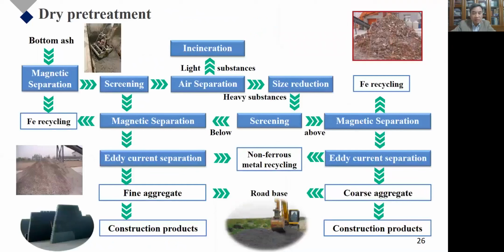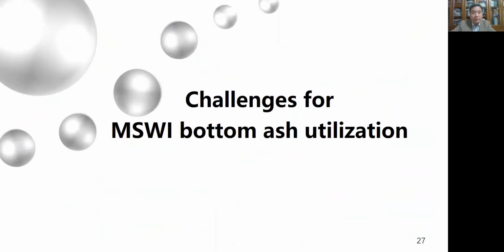In a few incinerators, the dry pretreatment method is adopted, which includes screening and size reduction, air separation, and magnetic and eddy current separation. The aggregates are well graded, so they can be used as road aggregates or other substitute aggregate in construction products. Two-stage eddy current separation is usually adopted, for which the recovery efficiency of non-ferrous metals from the bottom ash with size less than 5 millimeters is not satisfactory.